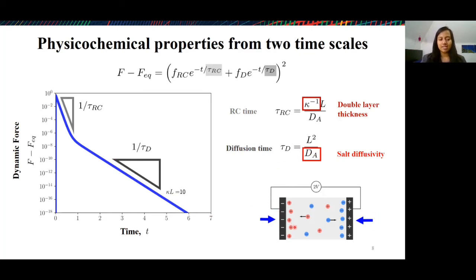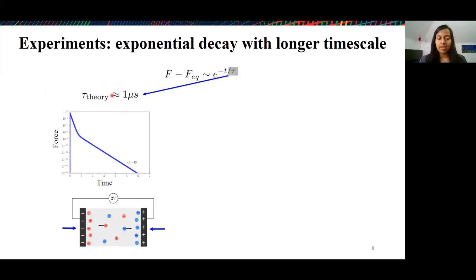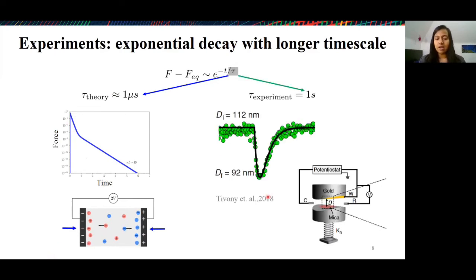So let's take a step back and look at how this actually compares to experimental results that I mentioned previously. Once again, we have our theory, which predicts an exponential decay along times, and we consider this model electrochemical cell under a suddenly applied voltage, and we're looking at the force between these two electrodes. An equivalent experiment was done by Tivony et al. a couple of years ago, where they consider a modified surface force apparatus, and they suddenly apply a voltage across these two surfaces and study the evolution of the system.